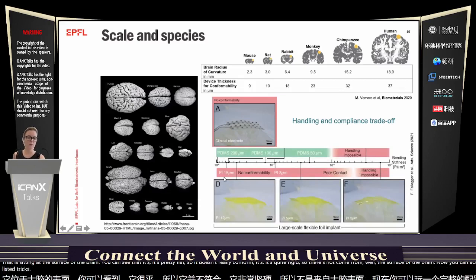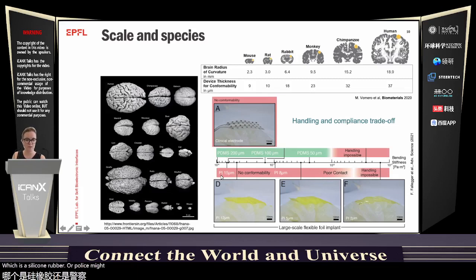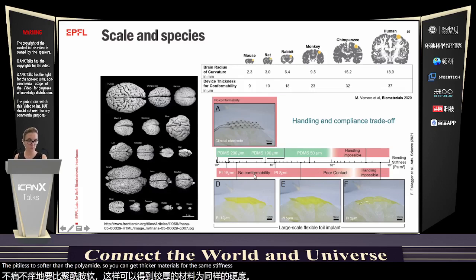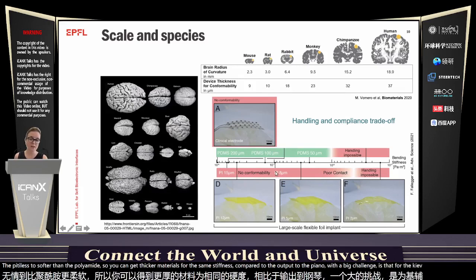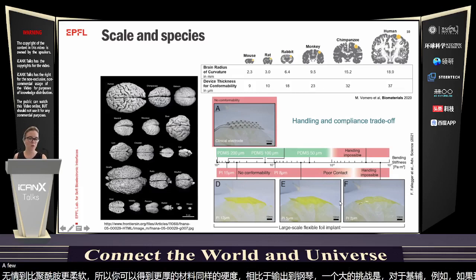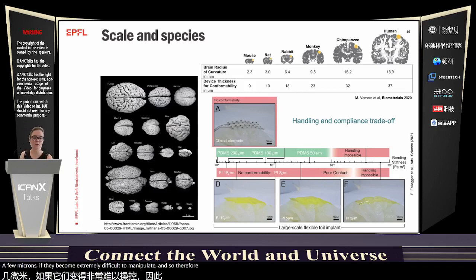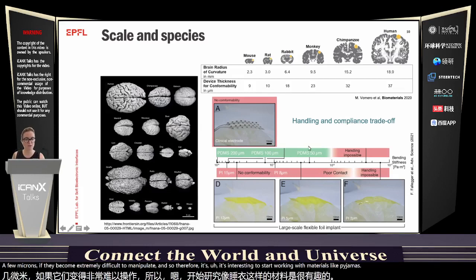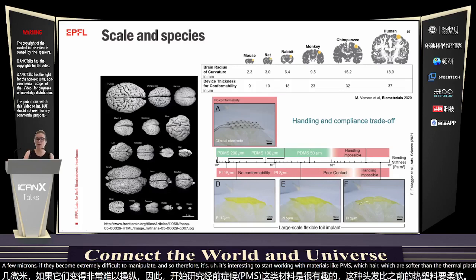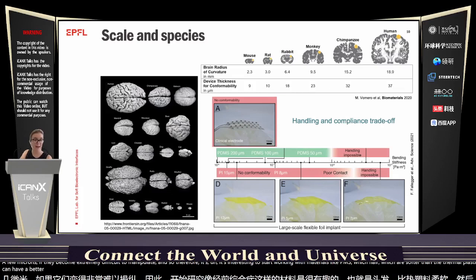Now, you can play with a whole range of configurations. Here we listed two typical materials that we use to fabricate such implants: PDMS, which is a silicone rubber, and polyimide, PI, which is a thermoplastic. Depending on the thickness of the material, you can compute the bending stiffness. Because the two materials have distinct elastic moduli, PDMS is softer than polyimide, so you can use thicker materials for the same stiffness compared to PI. The big challenge is that for PI, if we go very thin, typically below a few microns, it becomes extremely difficult to manipulate. So it's interesting to work with materials like PDMS, which are softer than the thermoplastics and allow you to have thicker membranes, so you can have better handling of your device.